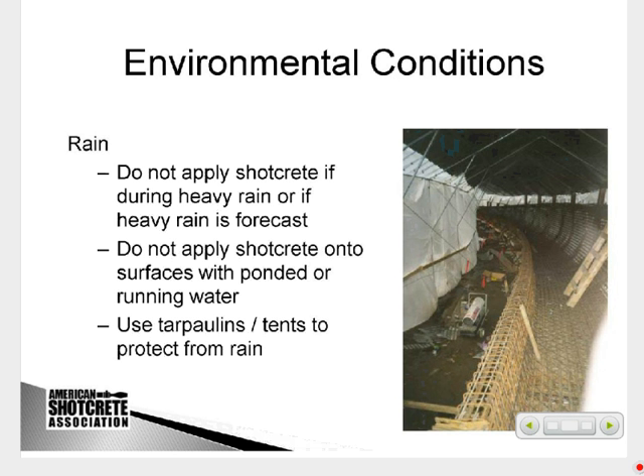Shotcrete does tend to have some benefit because of high cement content. We also use microsilica in a lot of shotcretes. Microsilica or silica fume is same material, different term. Helps to resist washout if you do get a rain.